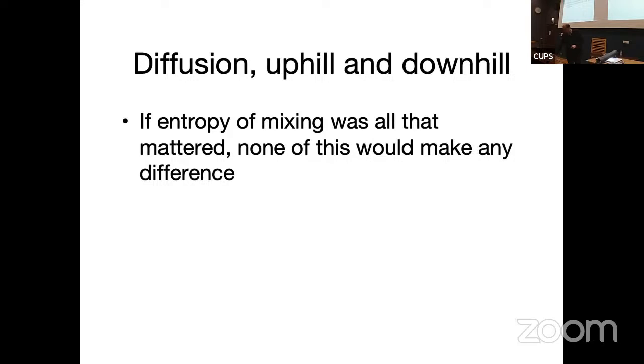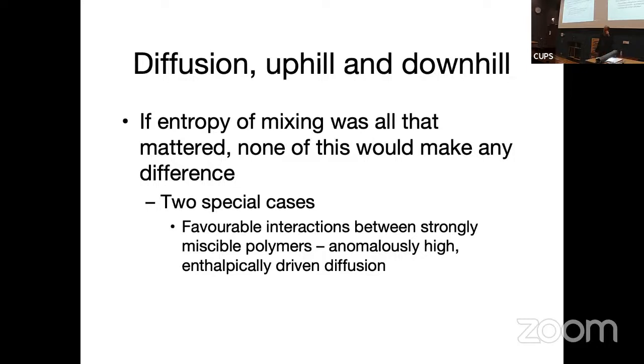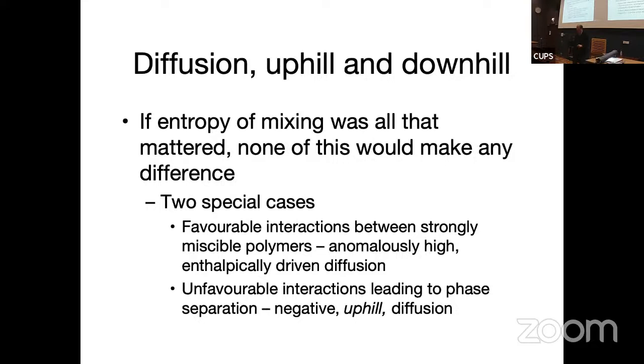There are two special cases. One is that sometimes, if you have very favorable interactions between strongly miscible polymers, and this only works for polymers for reasons that I'll show in a minute, you can get very high diffusion, which is driven not by entropy, but by enthalpy. It's by the fact that the molecules actually positively want to mix. But more interestingly, if you have unfavorable interactions, you can get diffusion that goes backwards. So you can get things that diffuse from low concentration to high concentration. And that turns out to be interesting and important.